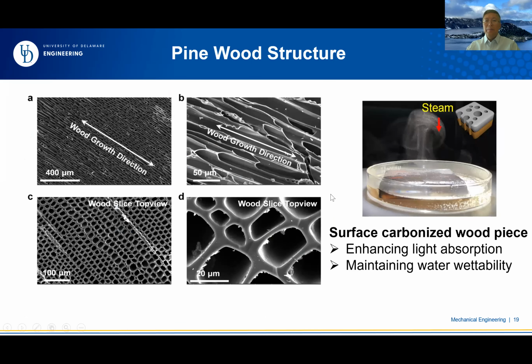Okay, so let me show you a simple pine wood structure here. You can see the microstructure of the pine wood has micron-scale channels, typically about 20 microns, and these channels can absorb water molecules and drive them through. This is a top view along the wood growth direction. You can see these channels are through channels.